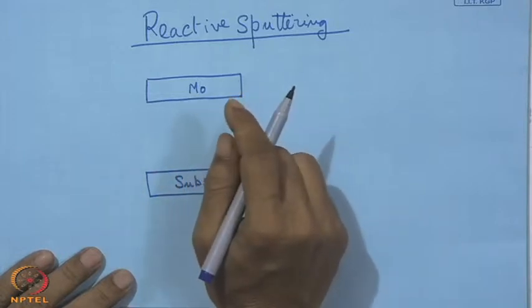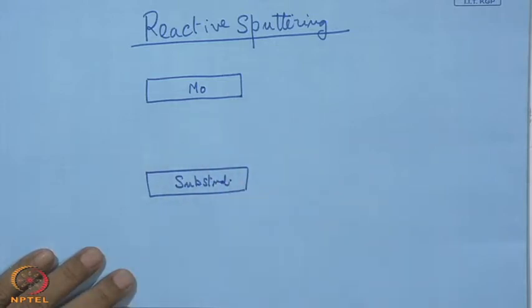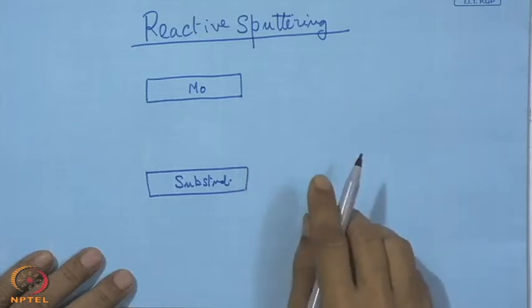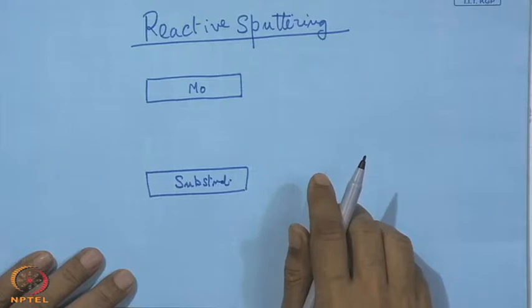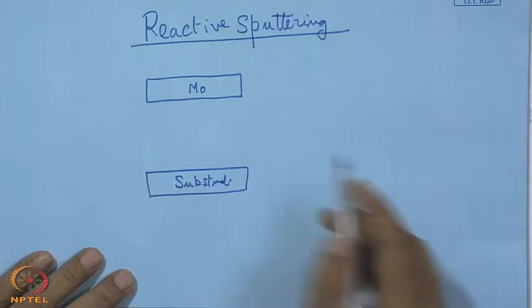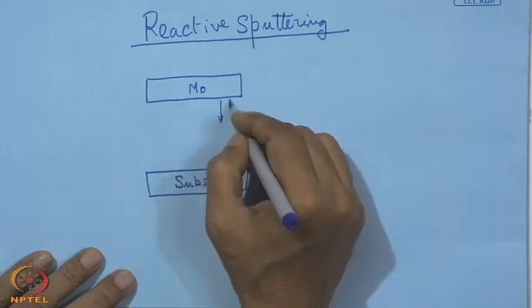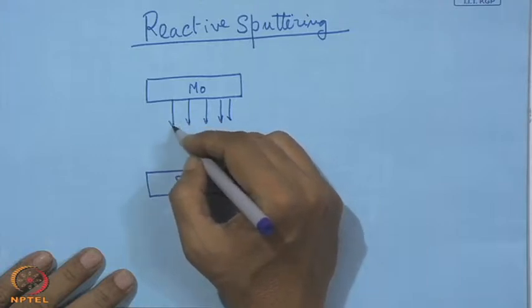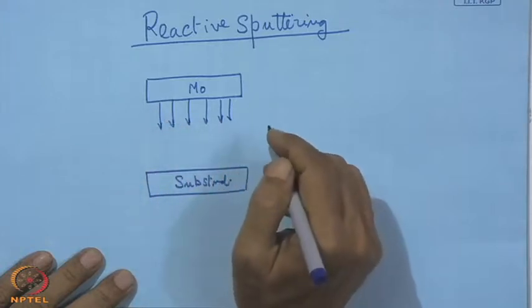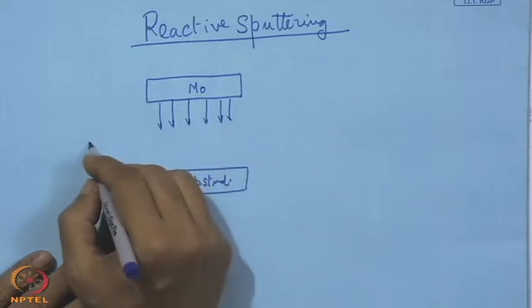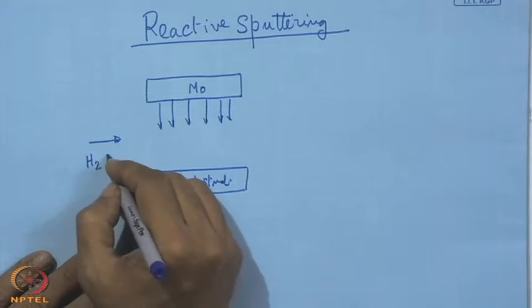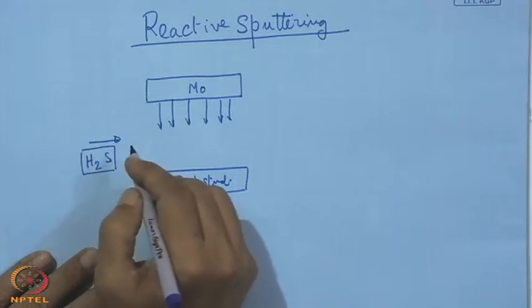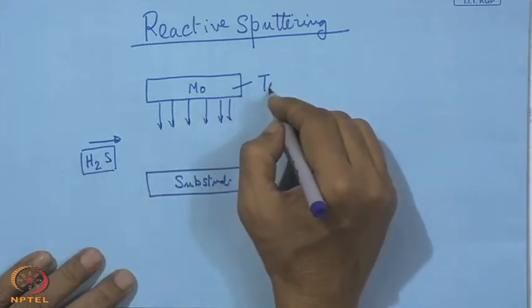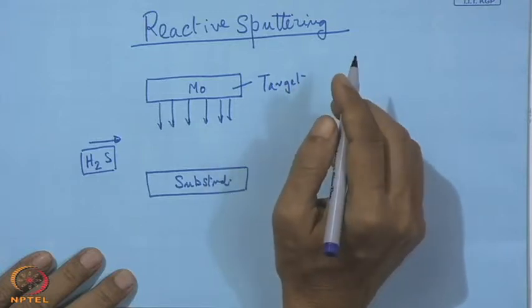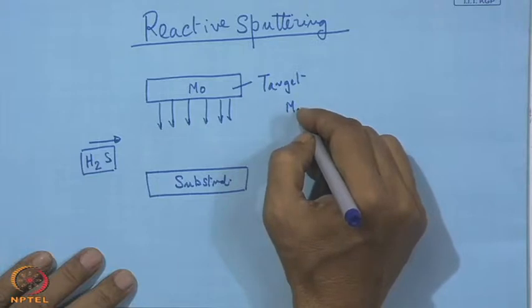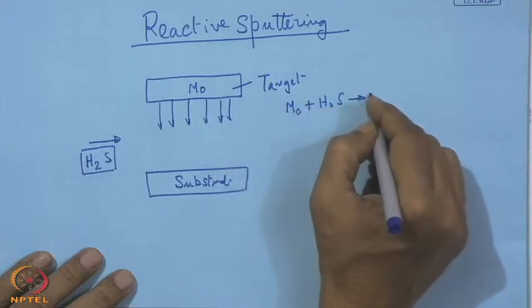And here, just like reactive deposition by sputtering, say for example titanium nitride deposition or aluminum nitride or chromium nitride or even molybdenum nitride, but in this case it is going to be molybdenum disulfide. So, Mo sputtered flux will come from this side, on its flight towards the substrate, and then what we have incoming, instead of nitrogen, will be H2S, that is the source of sulfur, and then this Mo from this target and this H2S from this external source can also make finally MoS2.